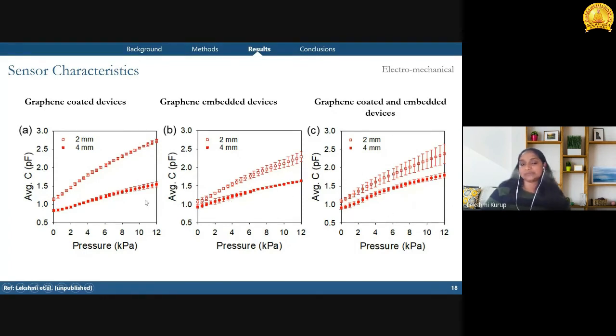This happens because as we apply pressure onto that material, at low pressure regions the pores start closing up to something like 6 kilopascal. Almost at 6 kilopascal, all the pores get closed. After that, if we increase the pressure, the PDMS material gets compressed, and this causes the increase in